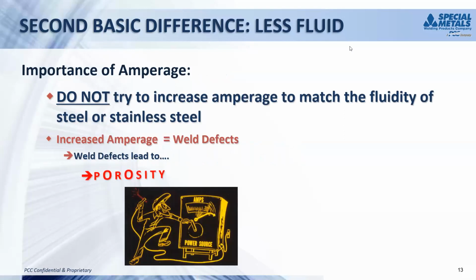So the first thing the welder will do, if he's not experienced with this, he'll say, well, it's obvious that I'm welding it too cold. I need more amperage. And so you turn it up and it's still cold. And you turn it up some more and it's still cold. And pretty soon, as you see in the little caricature, the welder has his electrode glowing red. And that's generally what happens. So we have to not try to make the nickel alloy weld like steel. We have to change our technique so that we don't get too high of an amperage and have weld defects, and certainly porosity. If you've ever had Swiss cheese, we used to illustrate that with a slice of Swiss cheese with porosity in it. Next slide, please.